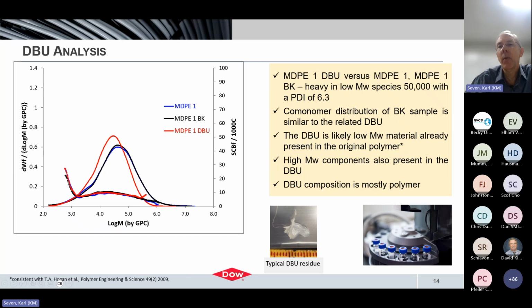So here, what we did was we looked at the die buildup sample itself. We wanted to get a better understanding of what was going on with the buildup. In the case where we were able to collect enough material of the buildup from the actual extrusion process itself, we tested that by GPC and characterized the molecular weight distribution. What we found, comparing the buildup versus MDPE1 and MDPE1 BK, was that the buildup does show a relatively high amount of low molecular weight species, with a PDI of 6.3.